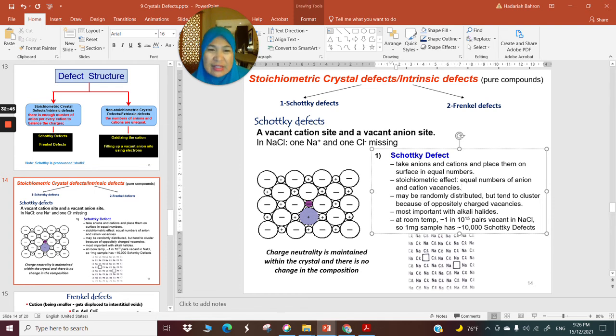The equal number of anion and cation vacancies will be randomly distributed, but they tend to cluster because the oppositely charged vacancies attract. This kind of Schottky defect occurs most importantly with metal halides, and at room temperature, about 1 in 10 to the power of 15 pairs are vacant in sodium chloride. So 10 to the power of 15 is extremely big. So you only get one Schottky defect in 10 to the power of 15. In 1 milligram of sample, you have about 10,000 Schottky defects.